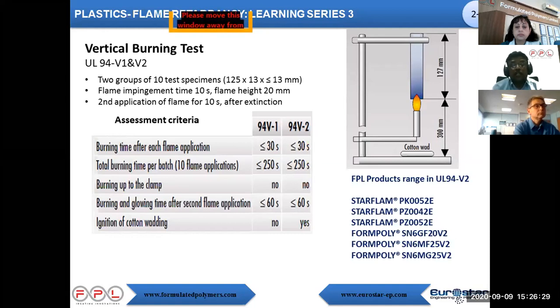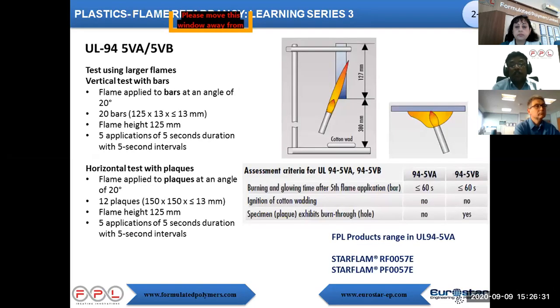And finally, we move on to 5VA, 5VB test details. Normally, this type of rating is required for highest concern areas like enclosures in stationary or fixed electrical live equipment. The 5VA, 5VB test needs to be conducted on both bar as well as plate specimens. Bar specimen dimensions are 125 mm by 13 mm width, like the previous HB and vertical testing. But the plate specimen should be 150 mm, depending upon the thickness of the part.